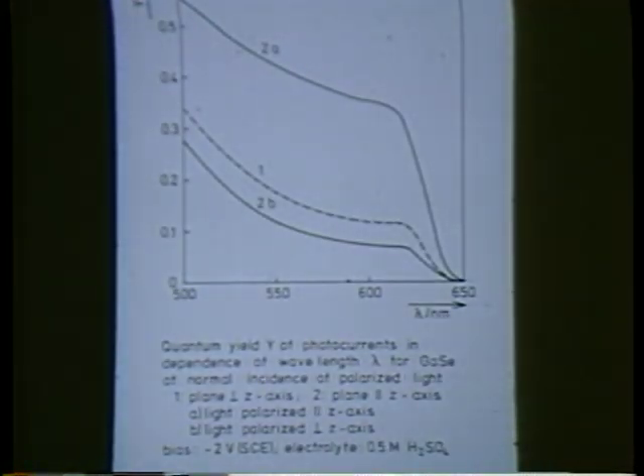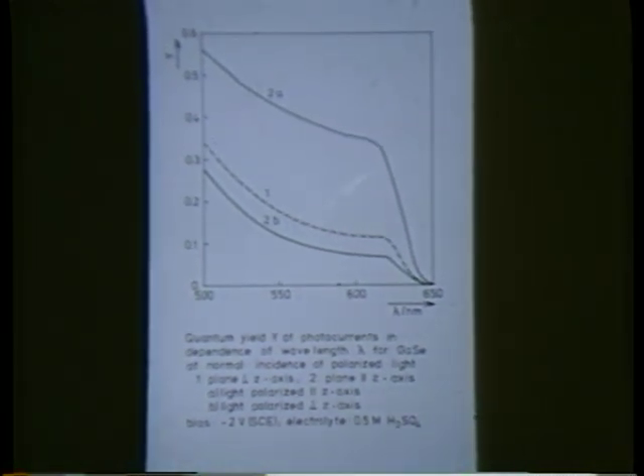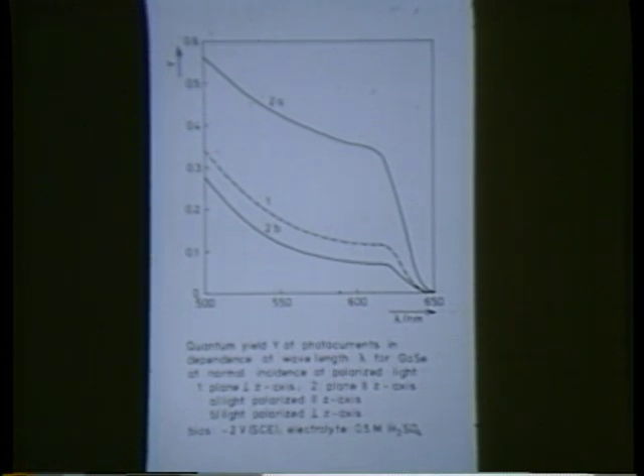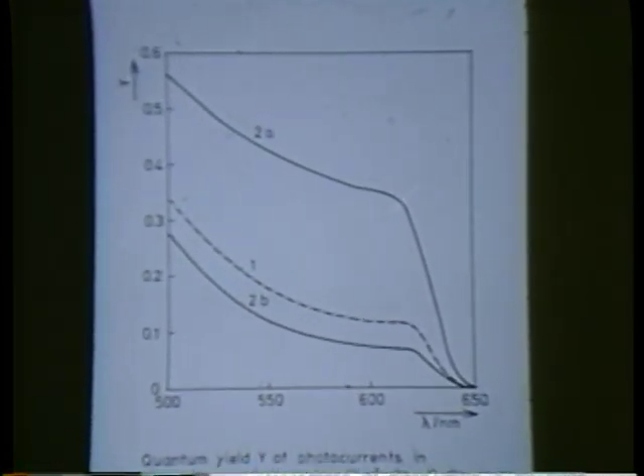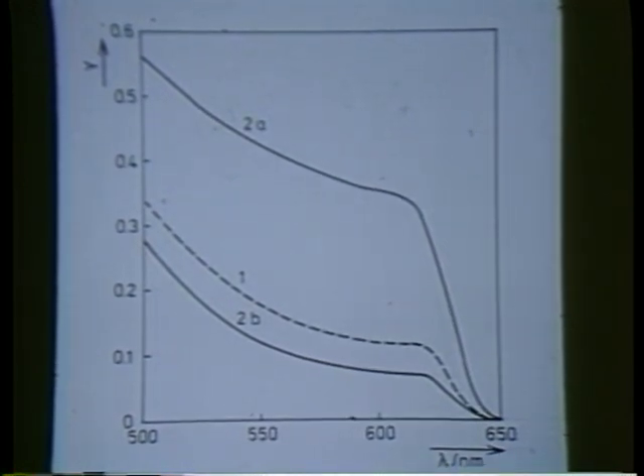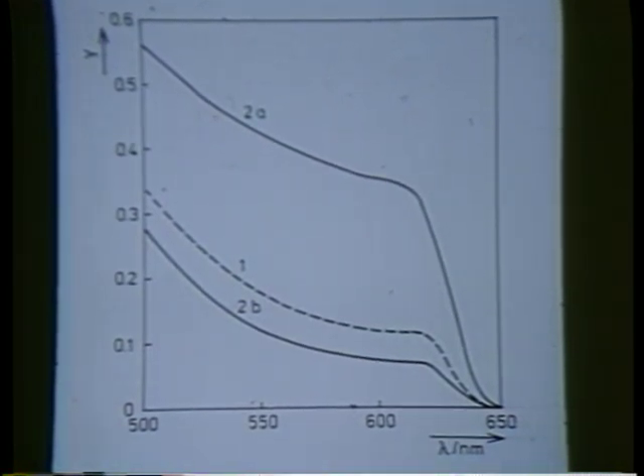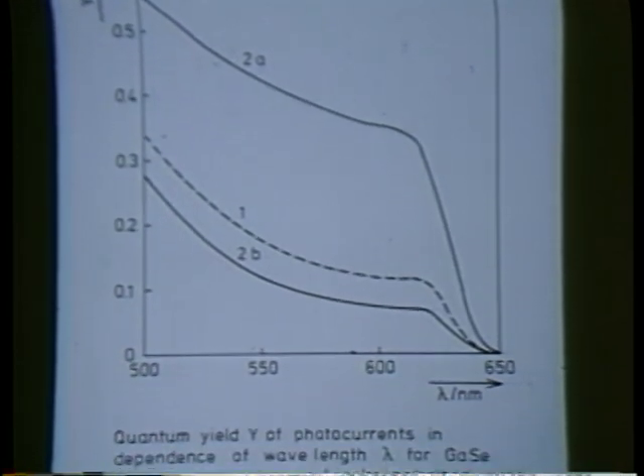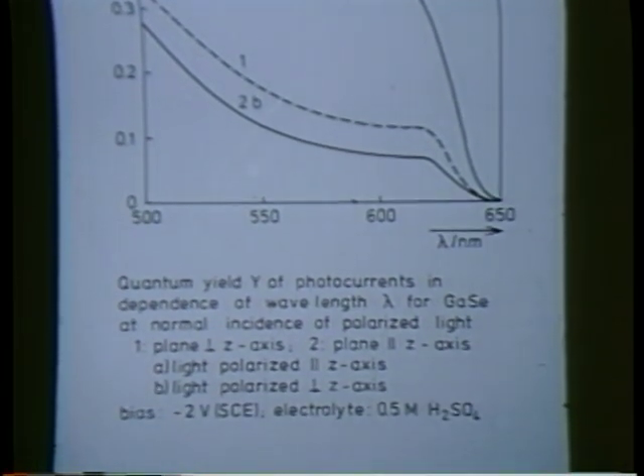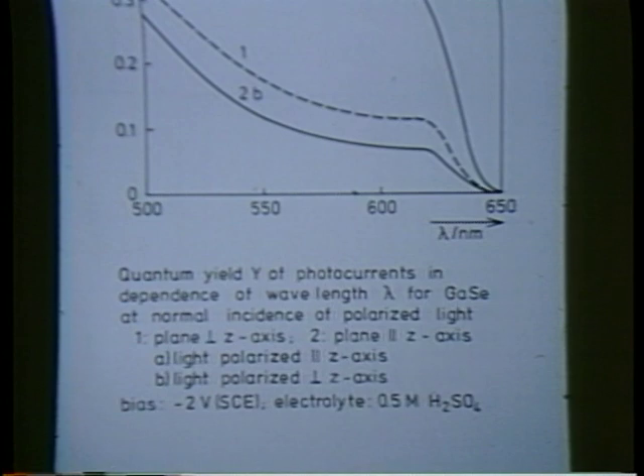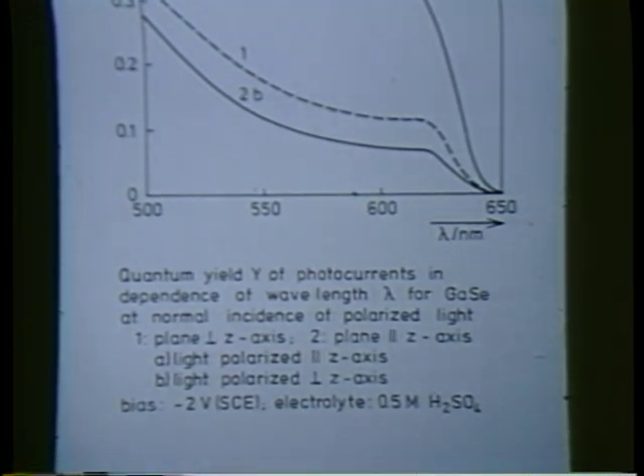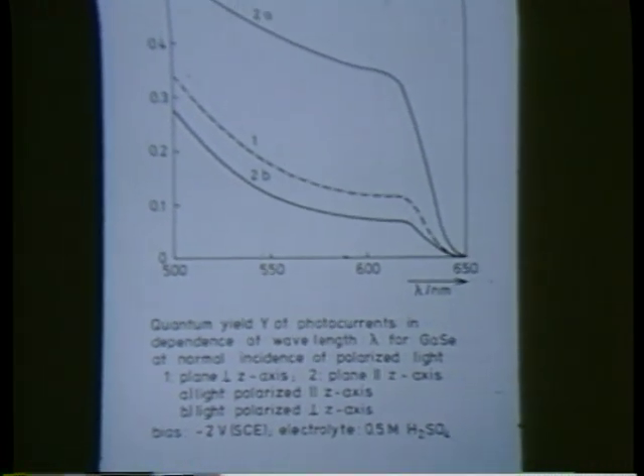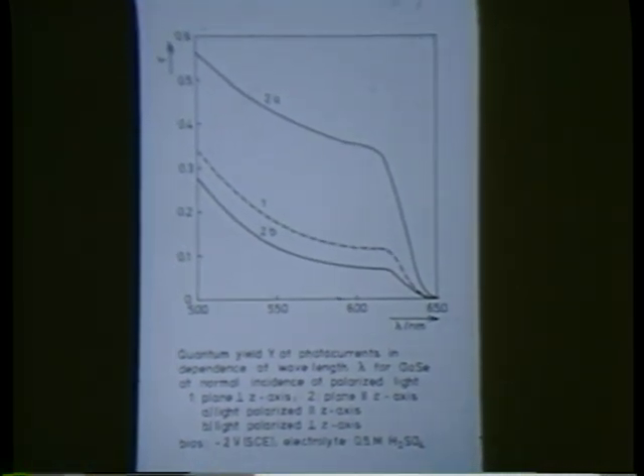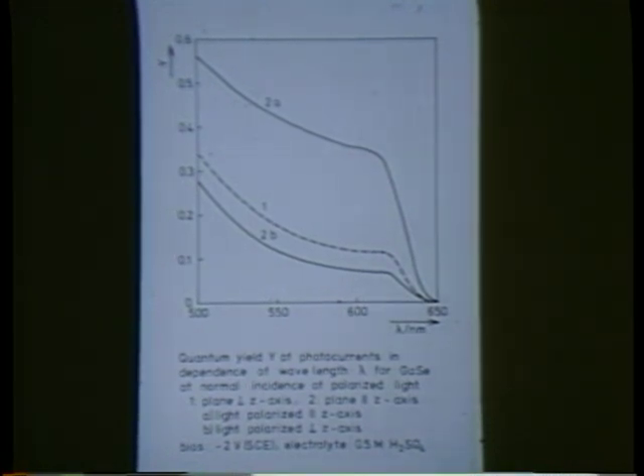And you see here, the photocurrent yield depends indeed very much on this orientation. And this curve with the highest yield is obtained with the same light beam on the side plane with E vector polarized parallel to the C axis, that is the highest current, corresponding to the higher absorption coefficient. So, from this difference, one can see what might be the difference in diffusion lengths in these two orientations. Now, so much about these, just as an example for applications of such measurements.